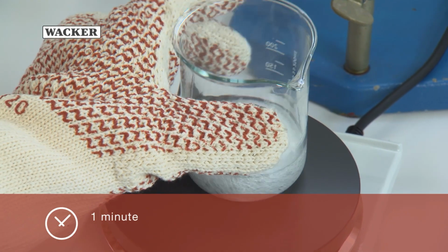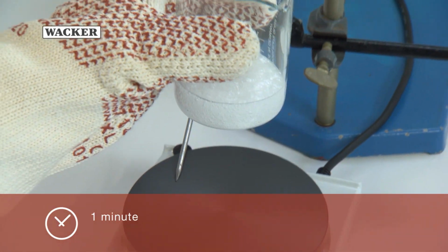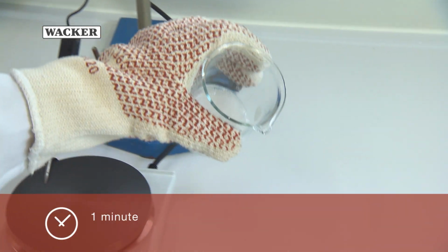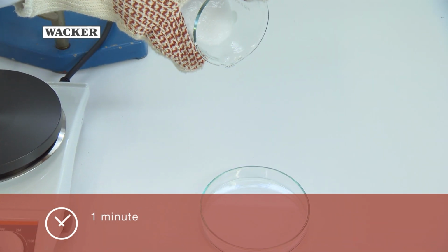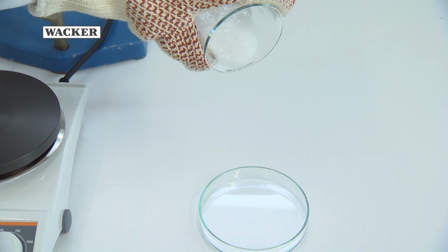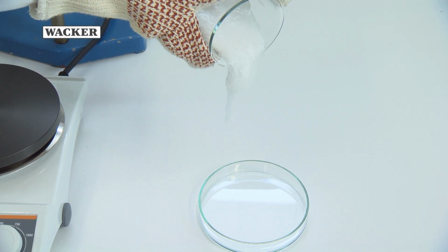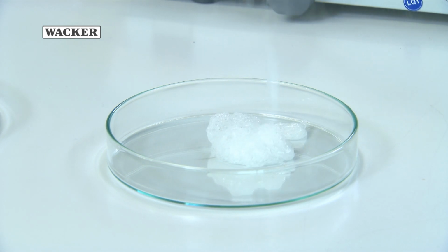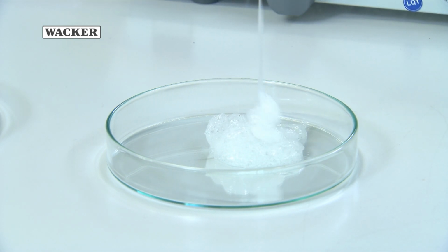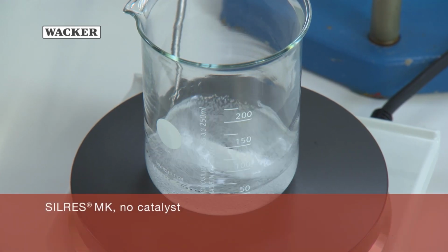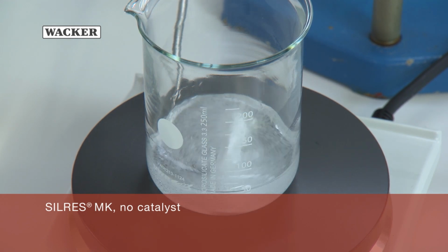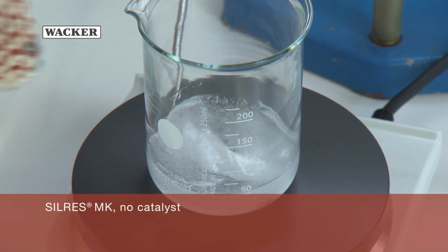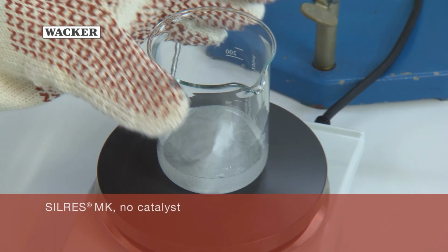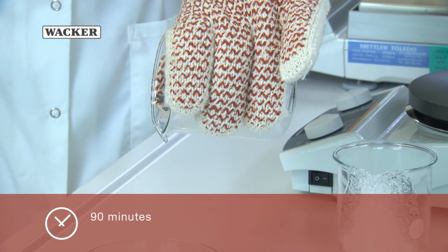Within only 1 minute of adding the catalyst, cross-linking has progressed to the point where the material begins to solidify. Molten uncatalyzed SILRES MK, by contrast, can be heated to elevated temperatures for relatively long periods of time with no significant rise in viscosity.